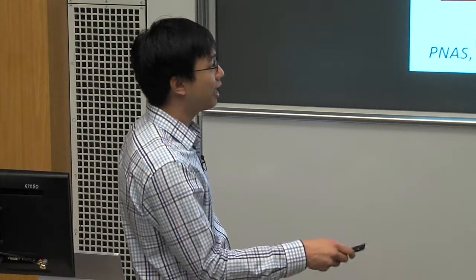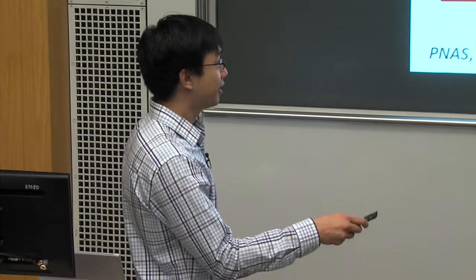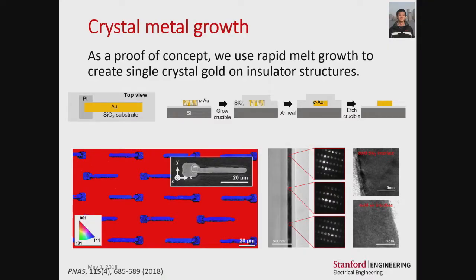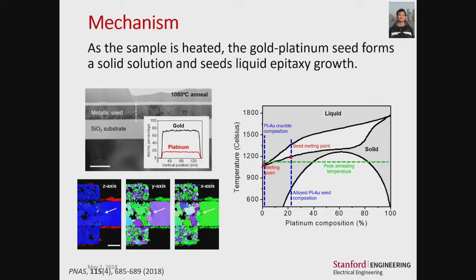though it is polycrystal. With this high-resolution TEM we can see very clear lattice fringes that are aligned with the oxide interfaces, which indicate a high degree of crystallinity and strong, again, 1-1-1 preferential orientation out of the plane, which is good, for example, for minimizing electromigration.